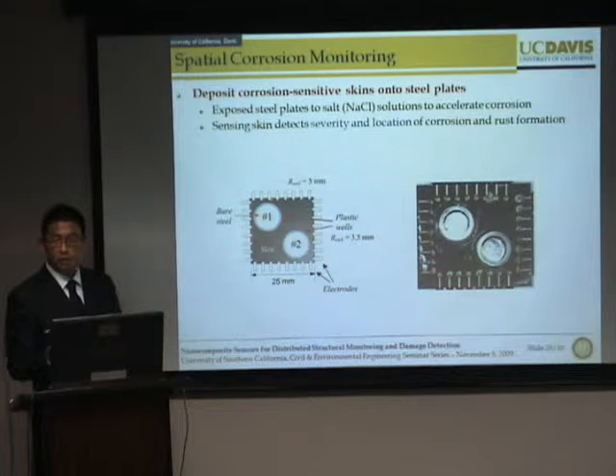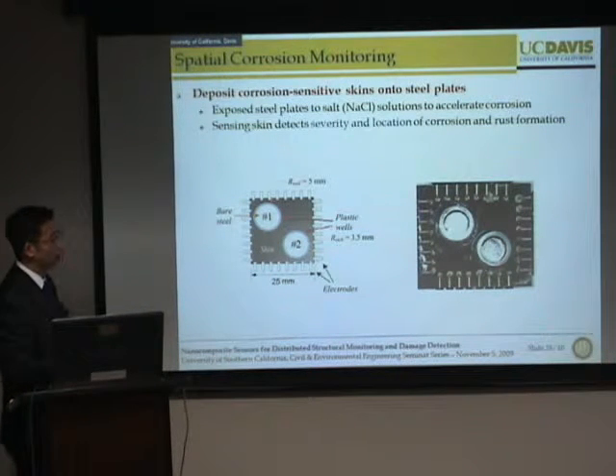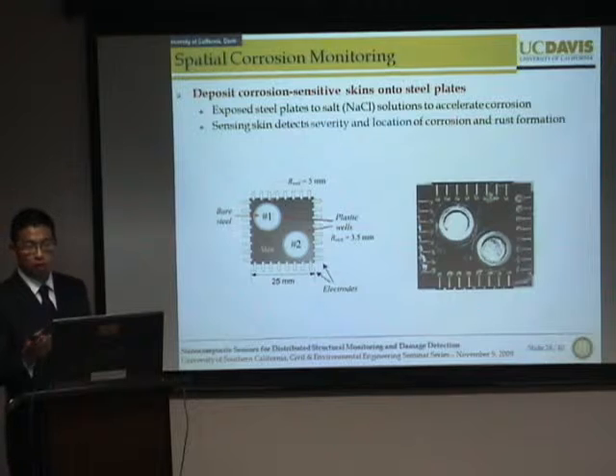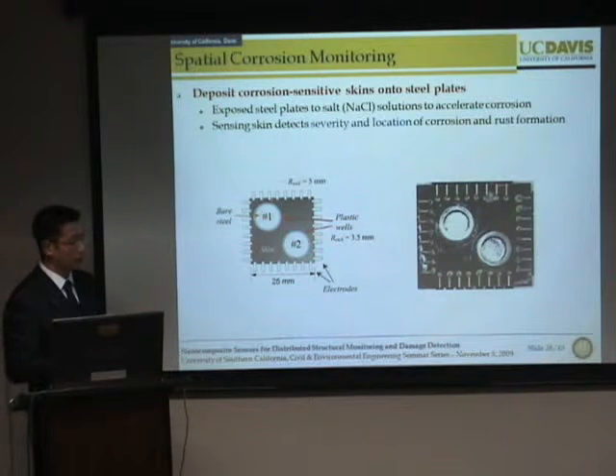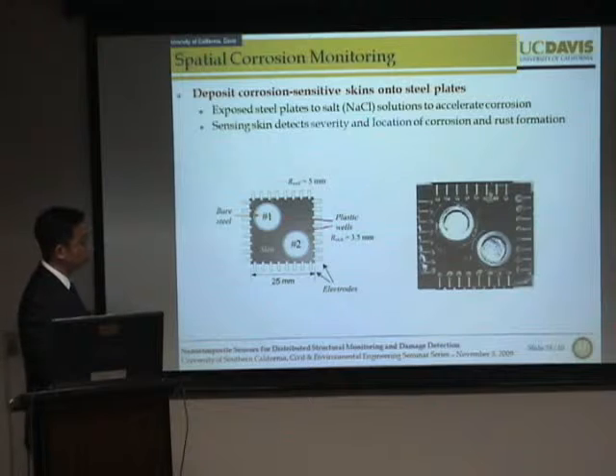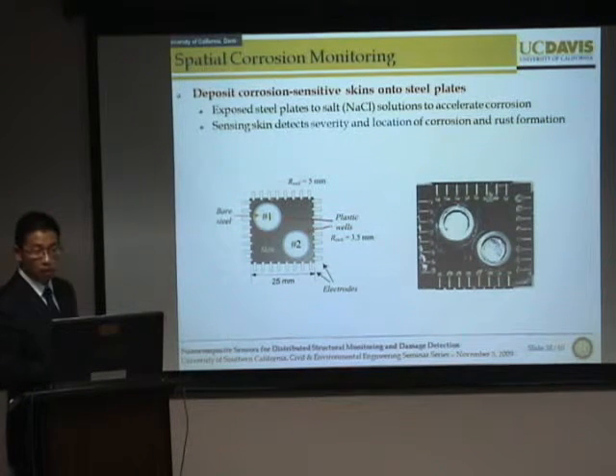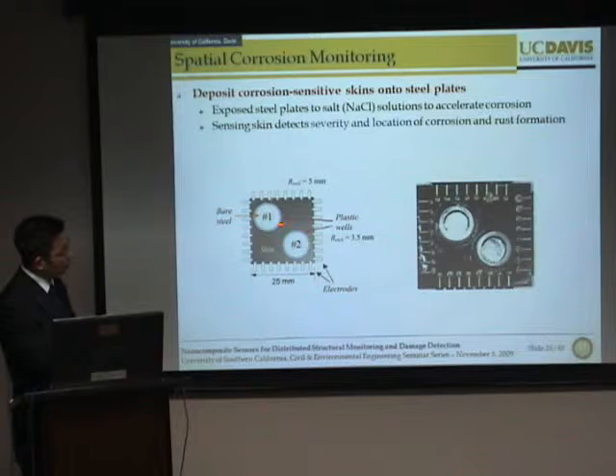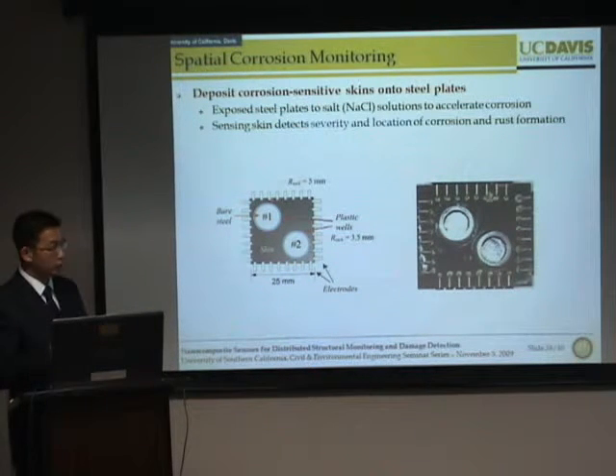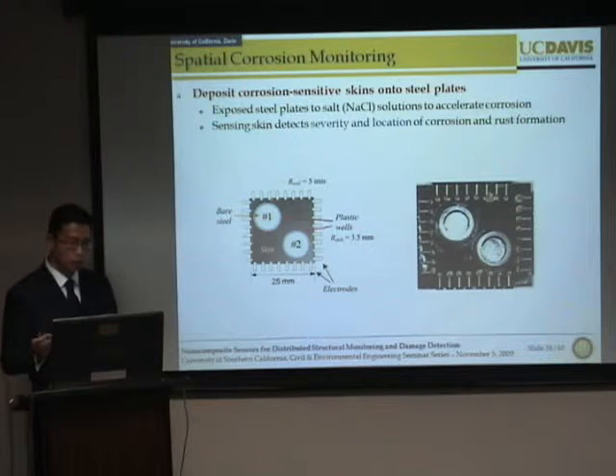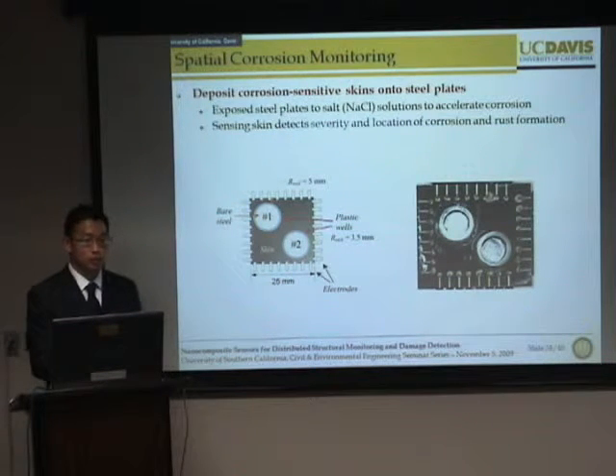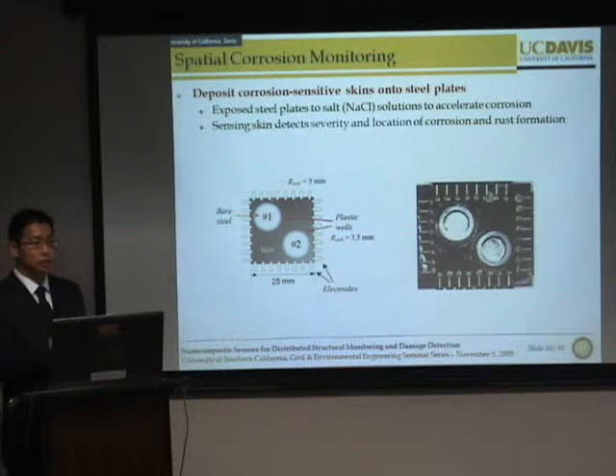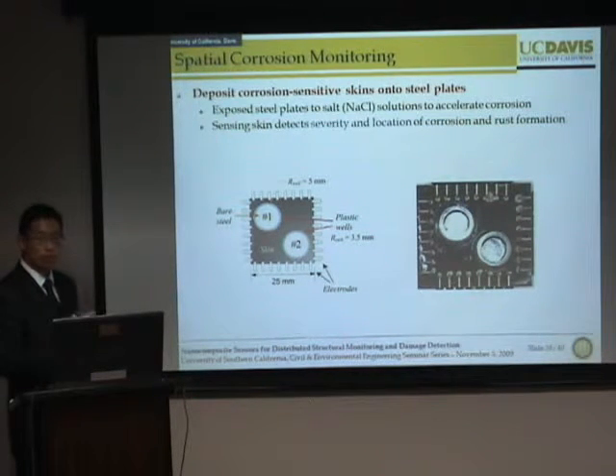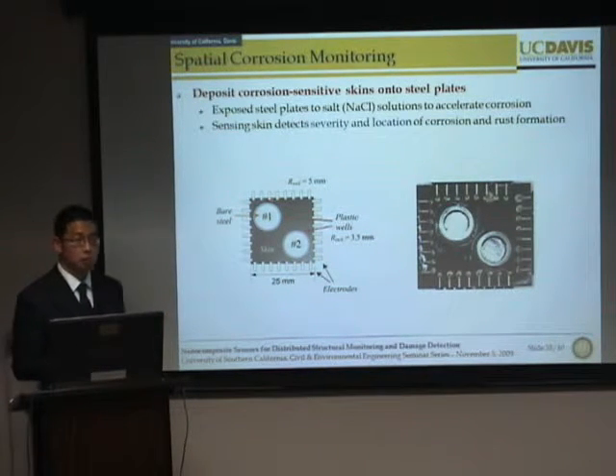Okay, so previously I also mentioned to you that we're interested in developing a corrosion sensor based on this polyaniline type of thin film. Now, in order to demonstrate that we can detect corrosion, we've deposited this thin film onto a steel substrate. We then etched out 2 regions on the steel substrate and mounted 2 plastic wells on the surface. The point of exposing the bare steel is so that we can pipette in different salt solutions to accelerate corrosion while simultaneously measuring the 2-dimensional spatial conductivity, to see if we can detect the growth of corrosion as well as where corrosion is occurring.